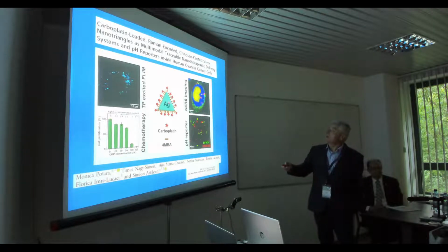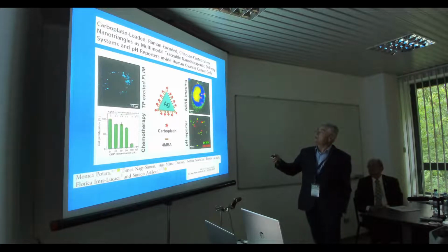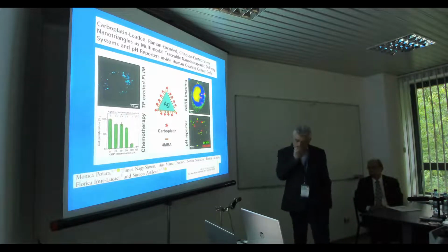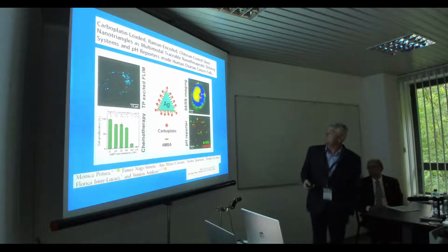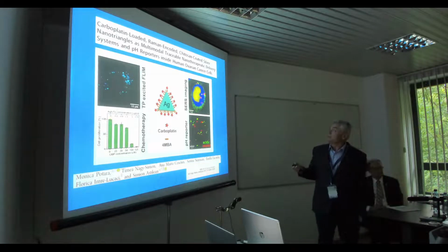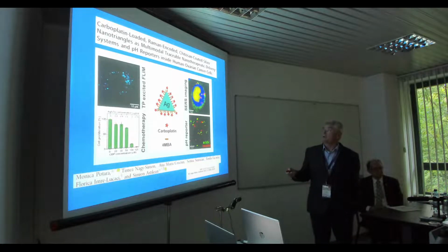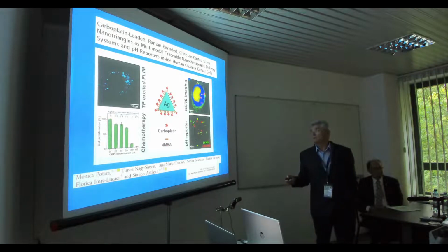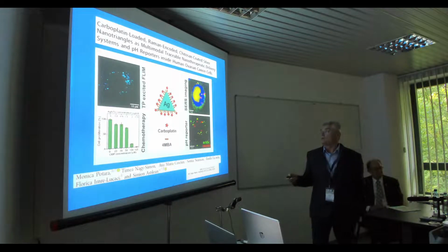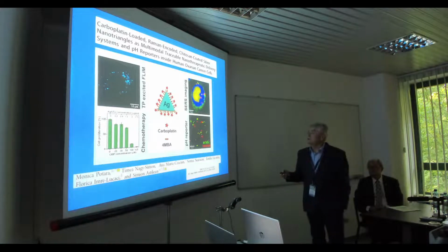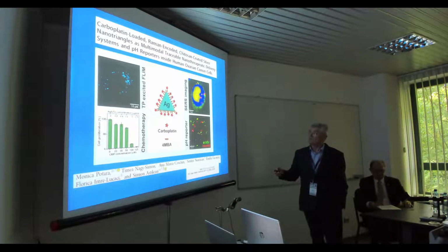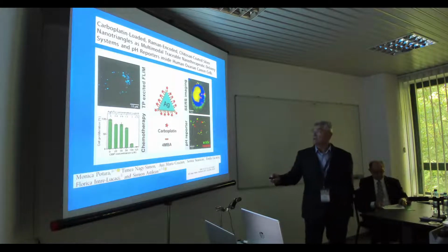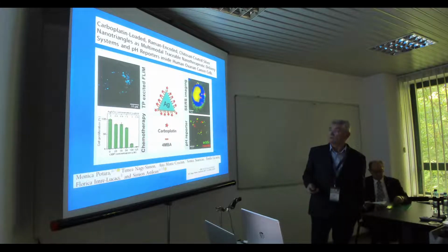Red spots are assigned to the nanoparticle, and the blue and yellow are the nucleus and membrane and so on. This is imaging of the cell. But very interesting results appear when you look specifically at the band of mercaptobenzoic acid. You can notice where the signal comes from, more acidic or neutral, inside the cell. So you can map pH inside the cell by using a specific reporter, mercaptobenzoic acid.